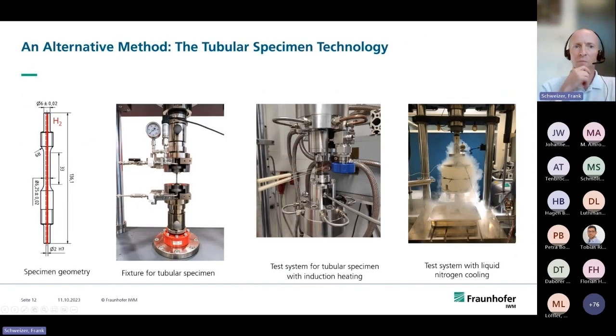An alternative method is the tubular specimen technology. As I said, you take a standard sample, make a long hole inside of it, and fill it with hydrogen, put it in a tubular fixture, and then the main advantage is, you can put different things around it, a heating chamber or induction heating, or also cooling to very low temperatures or lower temperatures as you like. So this is really good to handle.